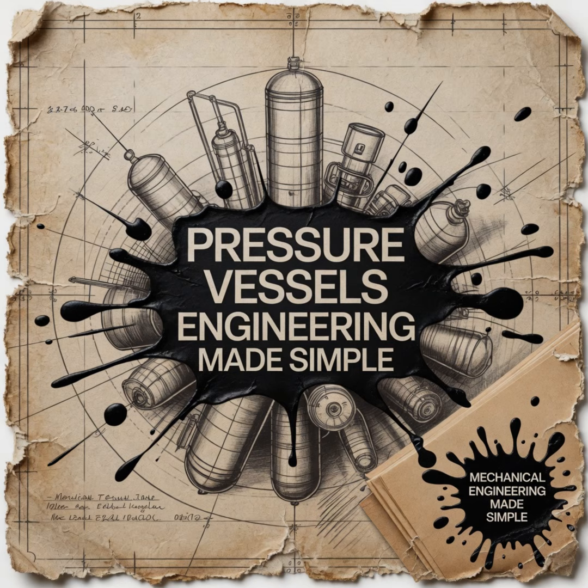What do they do with it? They X-ray it to check for porosity. Then they cut it into strips. They put those strips into a massive hydraulic tensile tester and literally rip the steel apart. They measure exactly how much force it took to snap it, proving it meets the minimum tensile strength. Then they take other strips and put them in a bending jig, violently folding the weld completely in half into a U shape. This proves the weld and the HAZ have the required ductility and won't crack under localized strain. Only if the test plate survives all of that destruction does the recipe get approved.